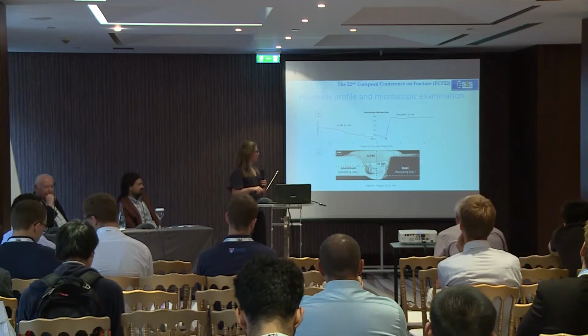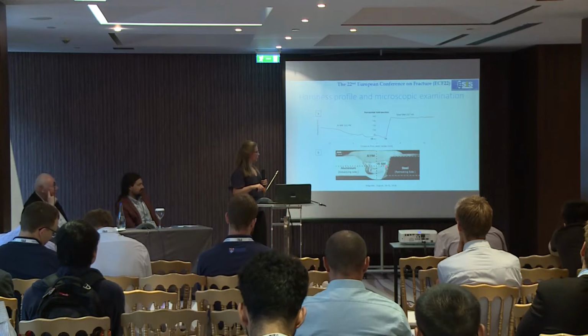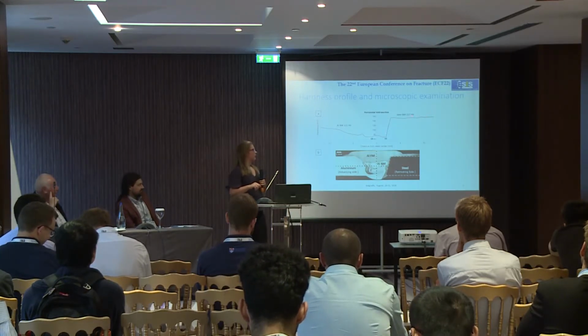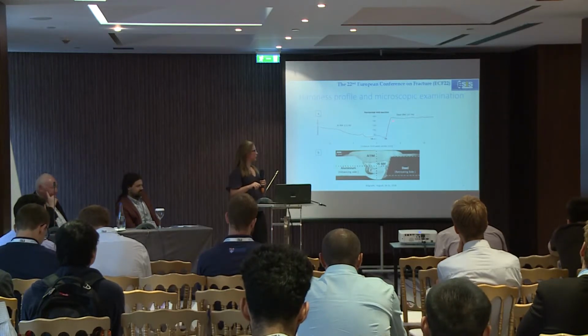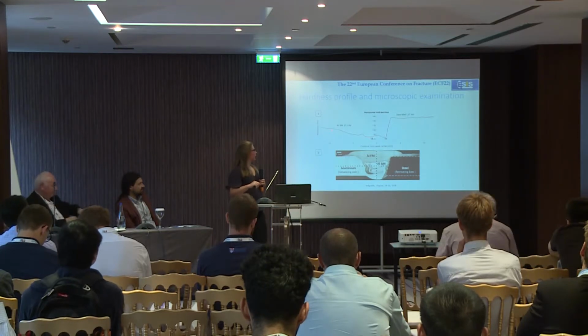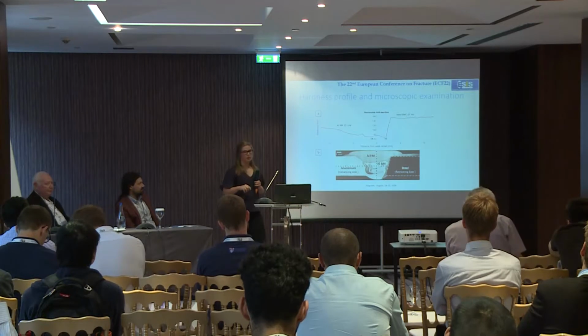And here you can see the hardness measurement along this line. As you can see, this is the lowest part on the transition here. And the steel seems also to be unaffected by the heat in the process and reaches its hardness immediately. On the aluminum side, you have a point that is a bit larger than this point, but still quite low. And the aluminum base material hardness is reached after about 12 millimeters, which is the extension of the heat affected zone.